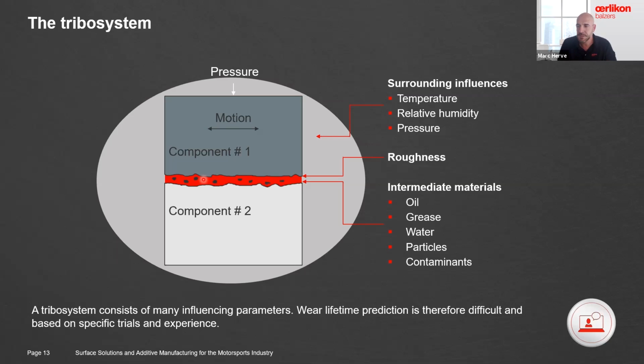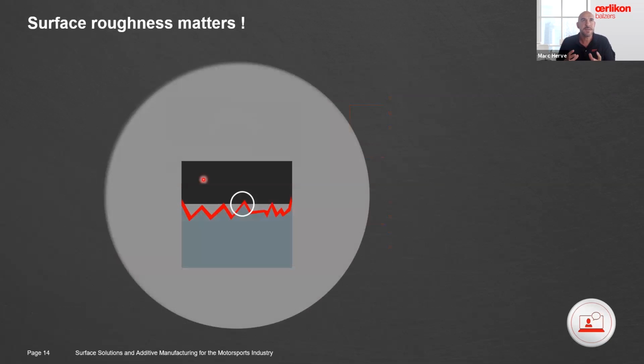So here is a very basic reminder of what a tribo system is. The reason I'm showing this is because when we talk about thin film, keep in mind we are talking about a few micrometers thick. Surface roughness, surface finish, actually matters, because the coating is going to reproduce exactly the surface finish that we have before the coating. If you get something shiny, highly polished, after the coating it's going to be the same. But if you get something very rough, the coating will just reproduce exactly the surface. So the risk is that at the end you have your coated parts with high roughness, and the coating will keep all the high peaks of the finishing.